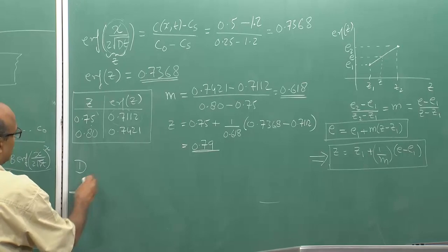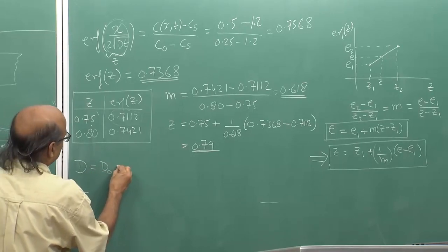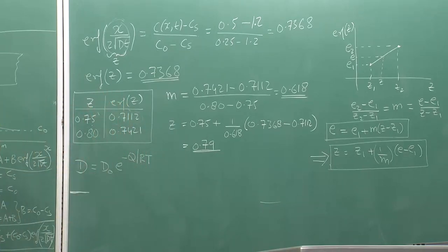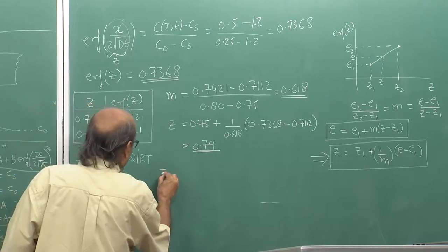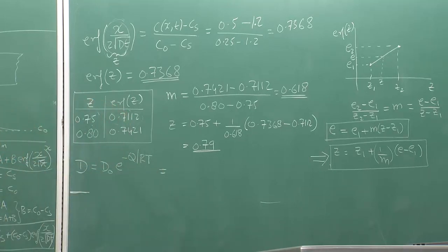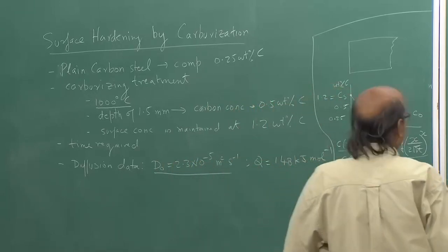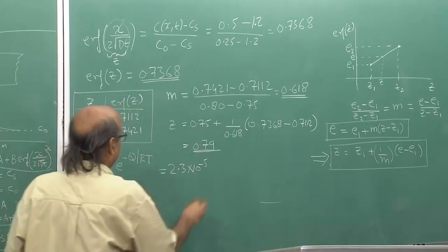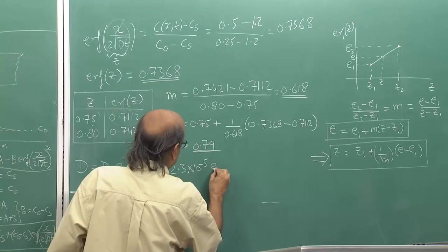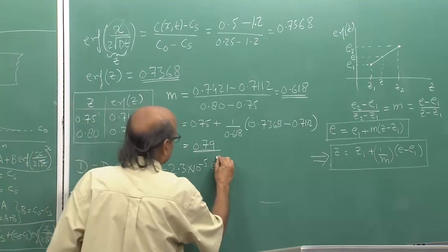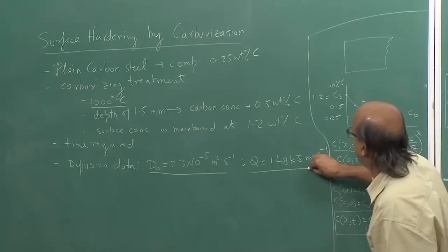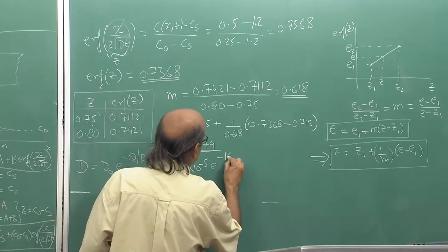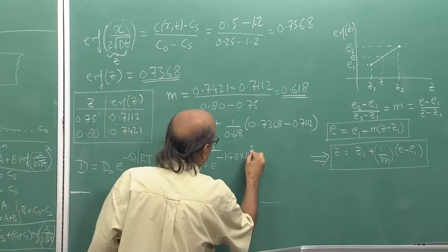The diffusion coefficient D is equal to D0 e to the power minus Q divided by RT. Now, let me write down what D0 is. D0 is 2.3 times 10 to the power minus 5 meter square per second, multiplied by exponential e to the power minus Q. Q is 148 kilojoules per mole. Convert the kilojoules into joules, so it is 148 times 10 cube